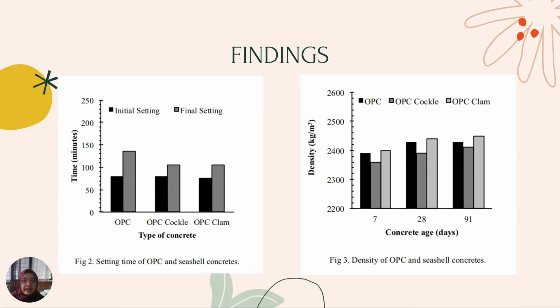Next is for the findings. As we can see here, the setting time for the OPC clam and OPC cockle were the lowest. This is due to the high calcium oxide content, which will increase the cement hydration reaction rate. And next is for the density. From here, we could see that the OPC clam were the highest. This is due to the calcium oxide content were high and thus reduce the porosity and increase the density of the specimen.